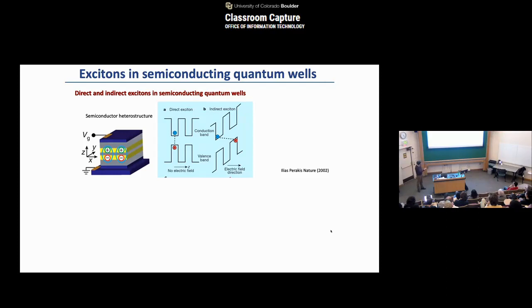If the barrier is high and wide enough, and there is good enough separation between the electron and hole in terms of suppressing wave function overlap, often this interlayer exciton can live reasonably long. Not forever, because there's still some finite overlap, but reasonably long, and that's already good enough to start to drive some interesting states.